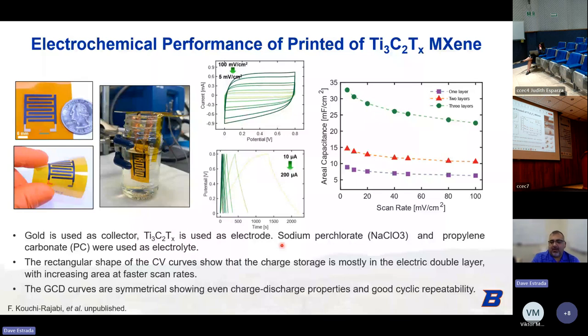For the organic electrolyte, we're using sodium perchlorate and propylene carbonate. And then we do the cyclic voltammetry to understand the capacitance behavior of this system. And so you can see here, the CV gives us a nice rectangular kind of response. And the GCD, galvanostatic charge and discharge curves, are also symmetric. And so this tells us that our charge storage mechanism is largely in the electric double layer.